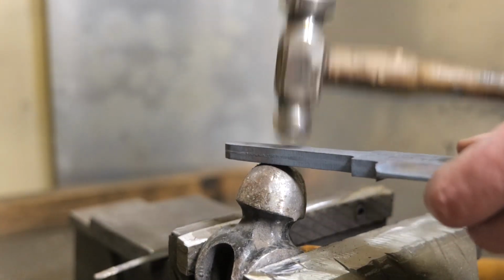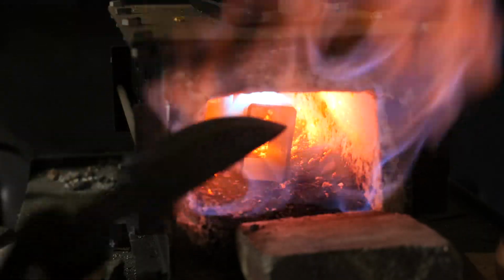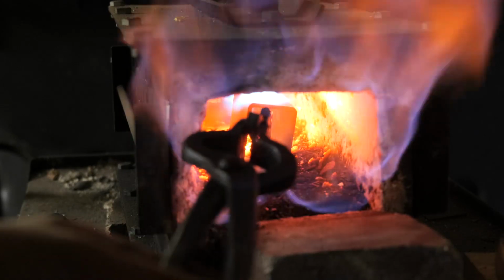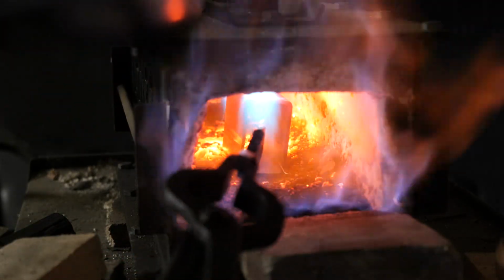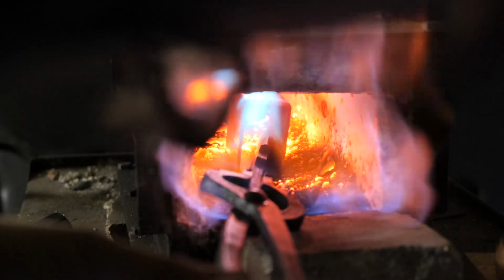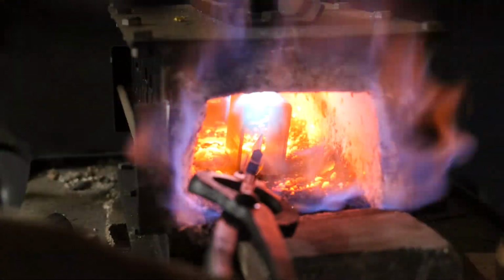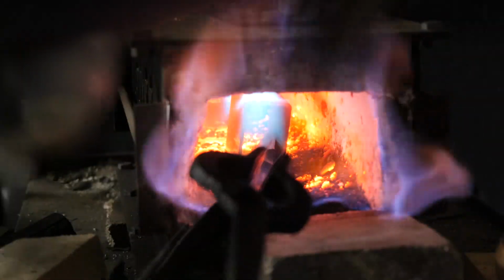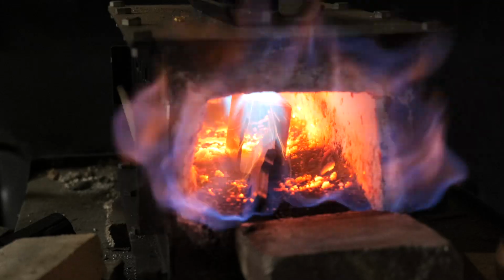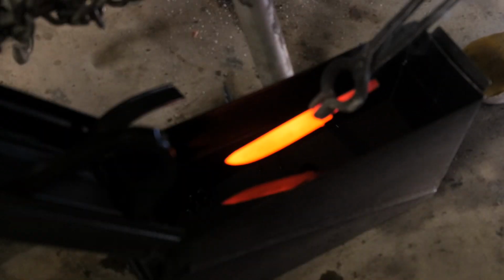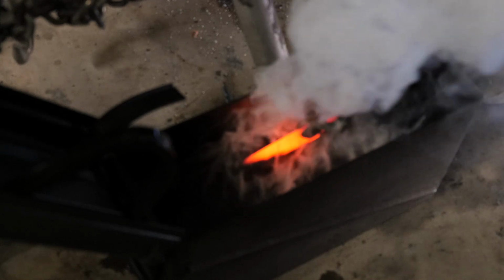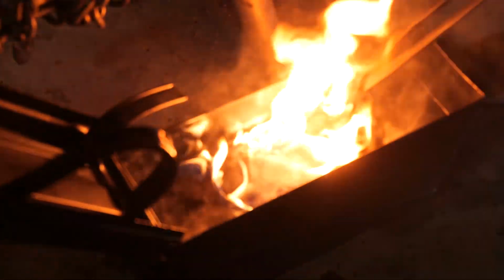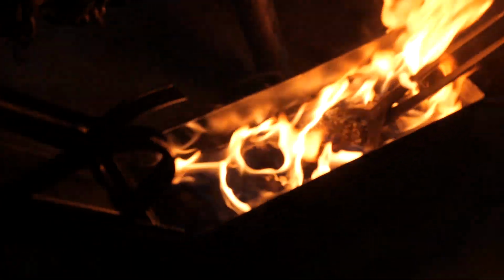So aside from practicing voodoo, another thing we can do to reduce splitting is to only bring the edge up to transformation temperature in the forge. The edge should heat up quicker than the jacketed portion since it's thinner, and since it is the only steel shrinking into austenite, there's less chance of the spine splitting, which is usually where the split happens. So the edge turns into austenite, but the spine shouldn't be getting hot enough to do this. Now, I don't think we were particularly successful here. I think it all got a little too hot, which is why I made a split decision just to do an edge quench here, hoping that would reduce some of the stress of at least the martensitic transformation along the spine. But the oil fire here had me quench the entire blade a little sooner than I wanted to.